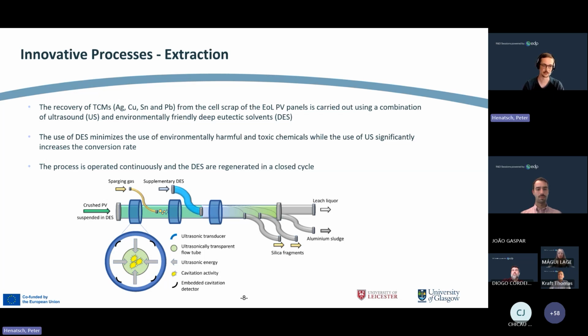Yes, in this picture here, you can see a rough sketch of the planned pilot line for this process step. So it's more or less a tube with the ultrasound generators around it, and the crushed PV suspended in the DES will get led through this tube to recover the silver, copper, tin, and lead from the PV cell fragments.